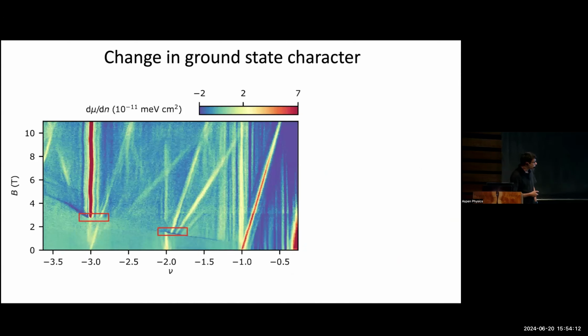The last thing I want to very quickly highlight is basically the role of what happens as you change the relative energies of these Moiré bands and undergo a magnetic transition. You can see at nu equals 2 and at nu equals 3, that's 2 and 3 holes per Moiré unit cell, there's an abrupt change in the electronic behavior as you undergo a magnetic transition. So this is saying that the nature of the correlated states that you get out, or even compressible states, some of these are metal insulator transitions, depends very sensitively on the magnetization of your carriers in your system.